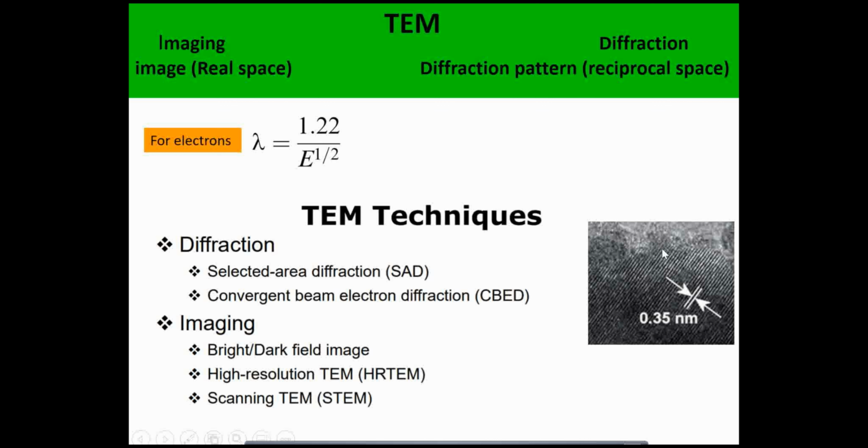In a localized area of the surface, whatever image we have in that area, we do phase contrasting, and then we generate some information out of it. That information is depicted here, showing us the lattice fringes, and the interplanar distances are being shown. You can see the interplanar distance here is 3.5 angstrom, or 0.35 nanometers. So we achieve high resolution by doing phase contrasting. So what is phase contrasting?